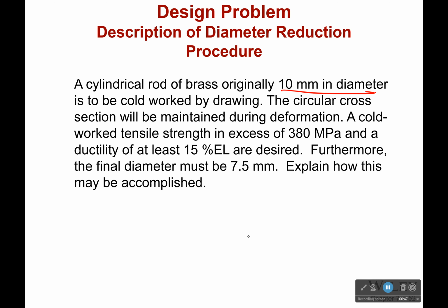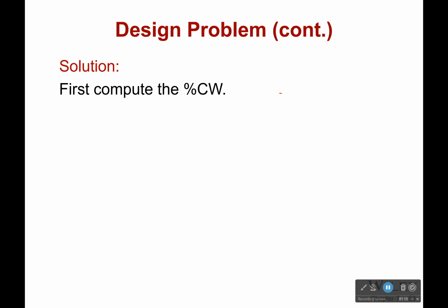So the circular cross-section will be maintained during deformation. We want a cold worked tensile strength in excess of 380 megapascals and a ductility of at least 15% elongation. And the final diameter must be 7.5 millimeters. Well, that helps us out somewhat. So explain how this may be accomplished. Well, I'm guessing it's going to have something to do with cold working and heat treatment.